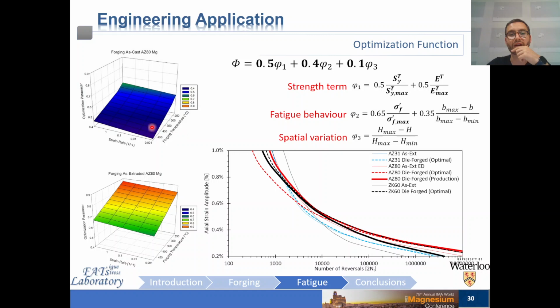However, you can observe how this result varies as a function of both temperature on this axis as well as strain rate on these axes, which are the two most critical processing parameters as I discussed previously. Selecting the optimum condition here would be that the extruded and forged material processed at 250 degrees Celsius and a strain rate of 10 per second would be ideal.